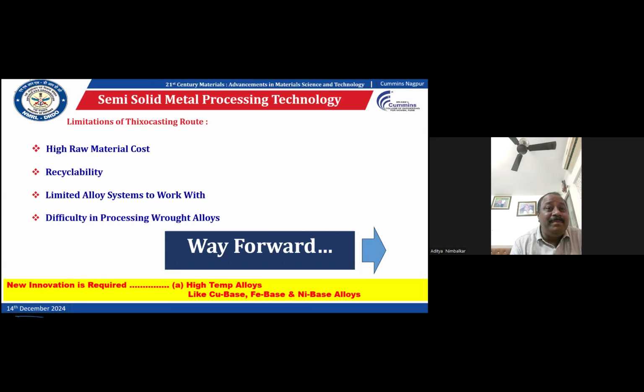So in this process, there are some disadvantages. One is billet making. After billet making, we have to cut the material into limited shapes, and we again have to carry out the reheating, and there is a restriction on the L by D ratio. Your material should be within a range. If your length is more, then after reheating, your slug will break in the middle. That is one major disadvantage, and the third one is how to transfer this material into the sleeve of the machine. Because there is a temperature of 700 degrees Celsius, even if you put on high temperature gloves, there is some problem for our workers. So there are lacunae in this technology.